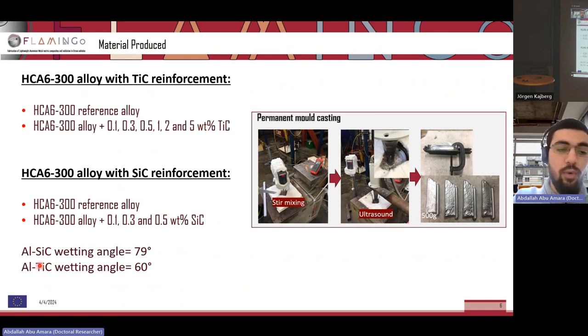As you can see here, I've put the wetting angles for an aluminium silicon carbide system and the wetting angle for an aluminium titanium carbide system. You can see that the wetting angle for the silicon carbide is much higher, 79, whereas for titanium carbide, 60. What this means essentially is it's easier for the melt to accept the particles, if you like. It's easier for that liquid melt to wet the particles. So we're able to achieve these higher weight percentages with titanium carbide.